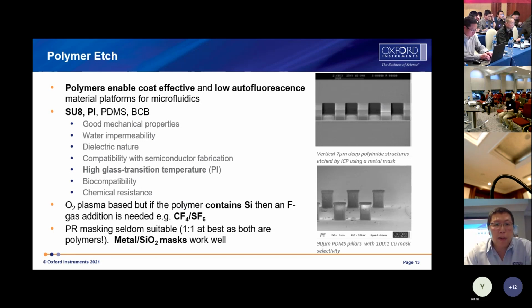Polyimide (PI) is an emerging candidate material, which also has good biocompatibility and chemical resistance. But this material has a very high glass transition temperature, up to 325 degrees C. As with etching SU-8, we use a similar oxygen plasma-based process to etch polyimide. Some polymers contain silicon, so we mix in some fluorine gas to remove this silicon-based material. A metal mask gives high selectivity.